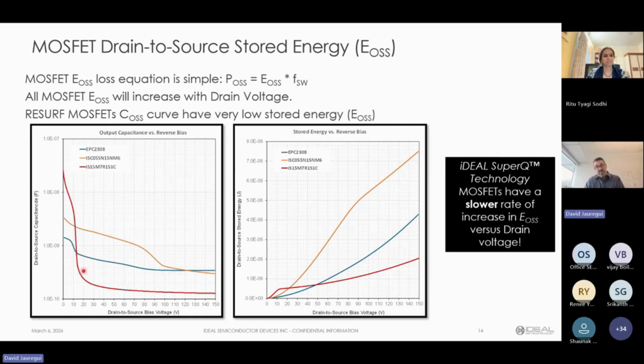Well, from an EOSS perspective, it's actually a very good thing because, once you do the mathematics and look at the amount of energy stored in the application or in that capacitance, you can see at low reverse bias, at 10 volts for example, our stored energy is higher than the other two MOSFETs. But all three MOSFETs here are rated for 150 volts, meaning that you're not only going to bias them at 10 volts, you're likely going to bias them around 90 to 100 volts. And you see that our stored energy doesn't rise as fast as the other two devices. You can see the Infineon device really just takes off when it comes to stored energy. And then the GaN device becomes, I guess, second place when it comes to this curve. So if you look at our stored energy compared to GaN, we're actually leading.